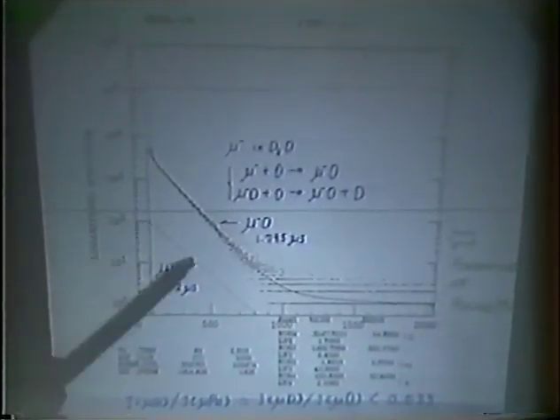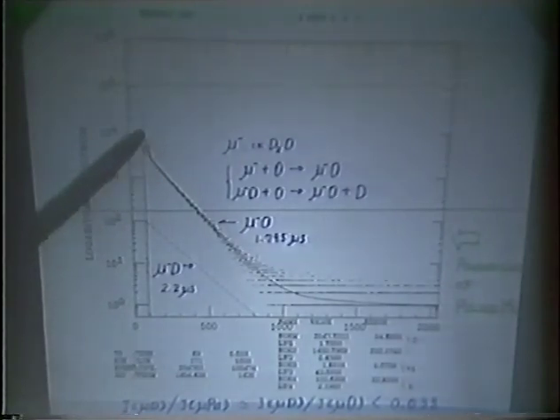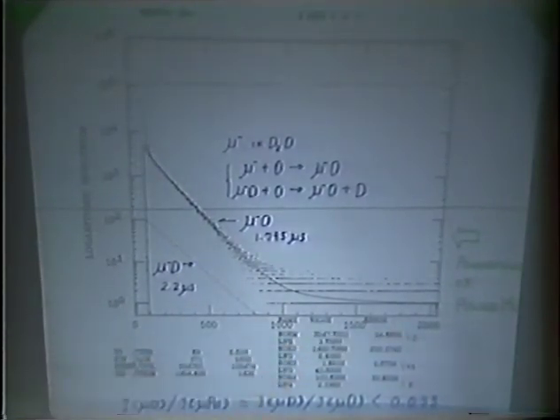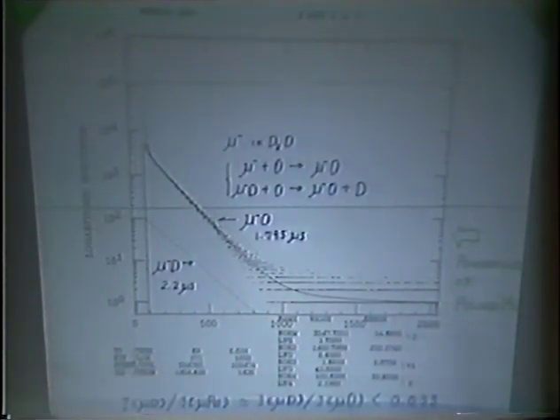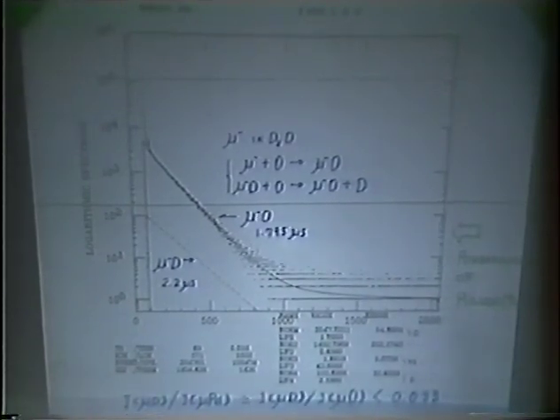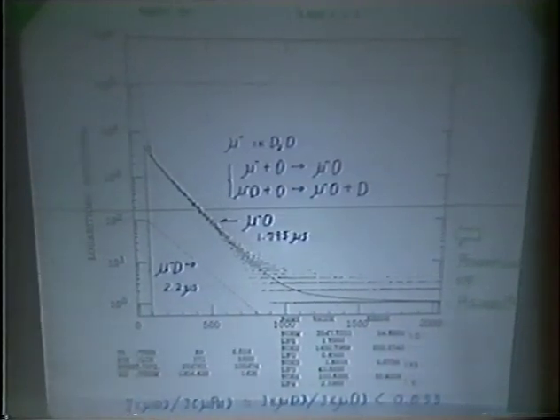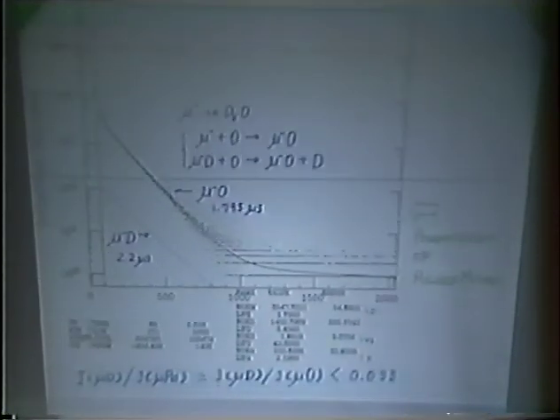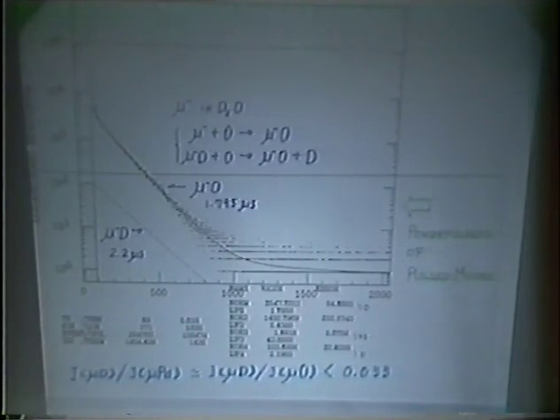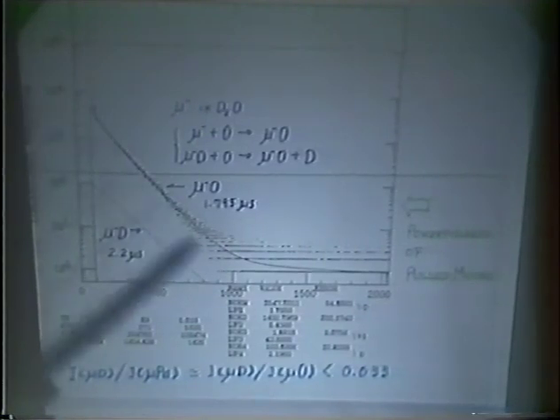This is not a 2.2 microsecond lifetime, but a 1.795 microsecond lifetime. This is mainly due to mu minus stopping in D2O. Mu minus D converts to mu minus O. Eventually, all the stopping events in D2O give us this lifetime of the signal. After making many lifetime component analyses of this lifetime spectrum, we concluded